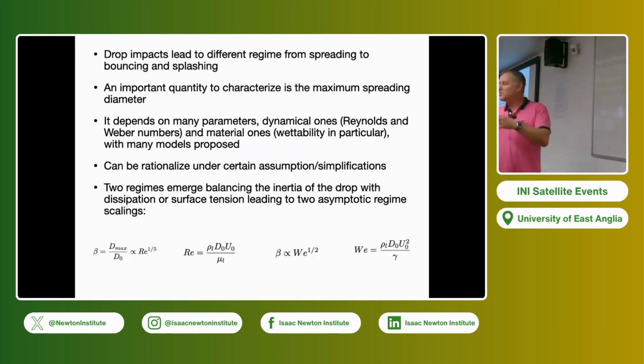So there was quite a lot of activity about understanding, when you have a drop impact, how much does it spread. There are a lot of applications in the sense that if you do inkjet printing, you want to control that. You also want to make sure that it is a circular line. So basically, understanding the maximum diameter of a drop that is impacting on a substrate is something you should at least understand if you want to understand these dynamics well. Basically, it depends on many parameters, and for the drop, this is mostly viscosity and surface tension compared to inertia that should drive this spreading. As dynamical parameters, you expect that the Reynolds and Weber numbers play an important role, but also the material on which you do the impact, that means the wettability.